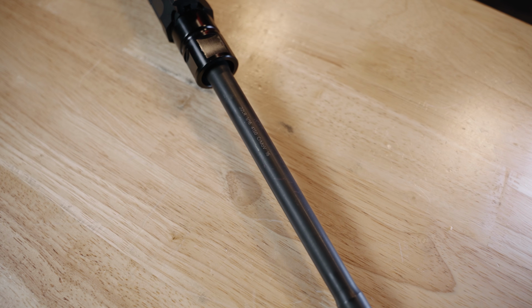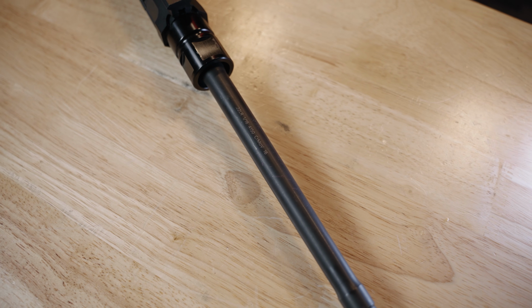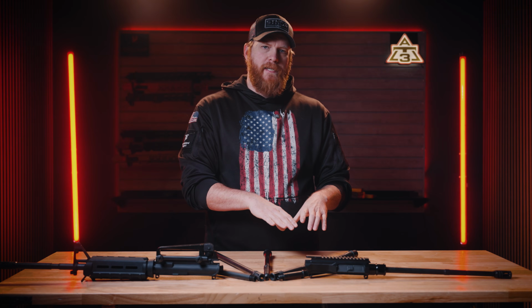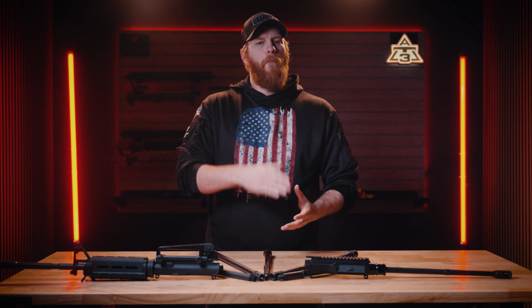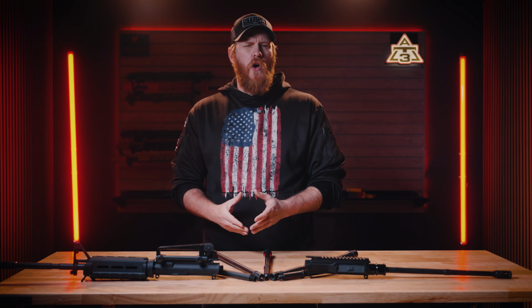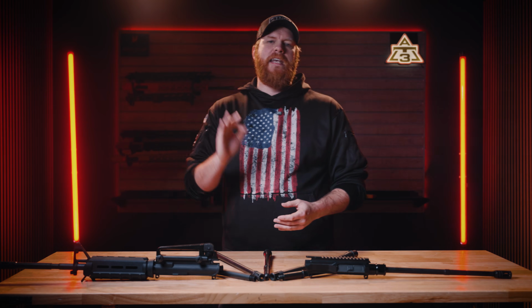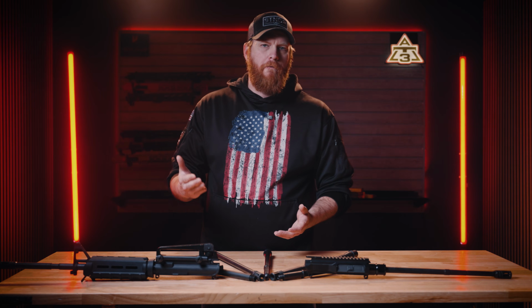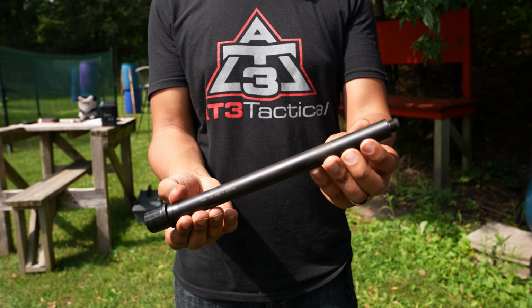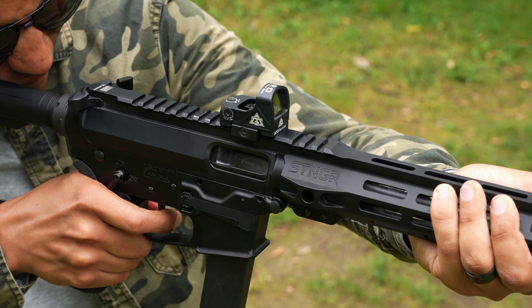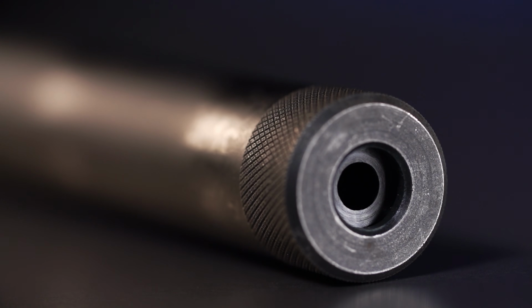Taking it up a notch from the standard CM barrel materials, we get to the 4150 Chromoly Vanadium steel, or just 4150 CMV. Not only are we increasing the carbon content of the barrel here with the additional 0.10% carbon, but we're also adding a small amount of material called vanadium into the metal mix. Usually this is going to be to the tune of 0.08 or 0.15%, which is going to help refine the grain structure of the steel and improve the wear resistance of the barrel, and also make the steel even tougher at those increased temperatures that you'll see on something like a duty rifle.